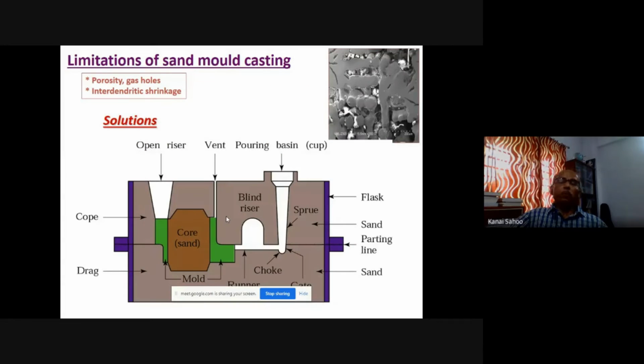Now you have to put the riser. But when you put this riser, people put a riser, but they never consider the design of the riser. You take care of the runner and all in the design, so that the riser material should be solidified last. Because when this metal casting solidifies, whatever shrinkage takes place, the riser should feed enough material to compensate that shrinkage. But in most cases, it is observed that this riser, this runner area is so small that it solidifies fast. So no use to put this riser. So please take care when you design a new cast product, when you want to really minimize the gas holes in your cast product.